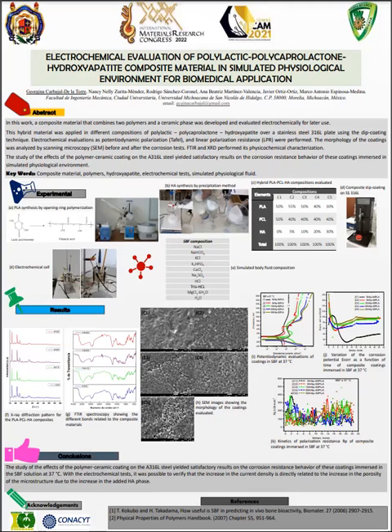Subsequently, the electrochemical behaviors of the composites were evaluated in simulated body fluid, with the compositions shown in Figure E. Each sample was evaluated for 40 minutes with a potential range from -500 millivolts to 2000 millivolts, a half cycle, and a scanning speed of 1 millivolt per minute. The X-ray diffractions and spectroscopies show that the materials obtained have high purity and corroborate the crystallinity of the phases.